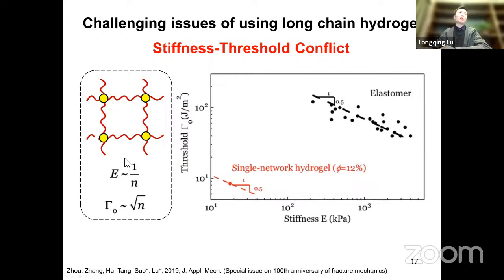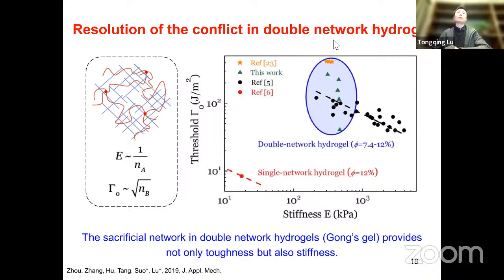Yeah, if you look at a single network hydrogel or a single network elastomer, the modulus is inversely proportional to the chain length. Means if the chain is very long, it's very soft. But the fatigue threshold is proportional to the square root of the chain length. So there's a conflict there. So actually many previous papers have studied this. They collected many data of different elastomers. This is stiffness, this is fatigue threshold, and we can see there's a conflict. For hydrogels, actually previously no people have studied this conflict. But of course, it's the same, the only difference is just a polymer fraction difference. So how to resolve this conflict for hydrogels?